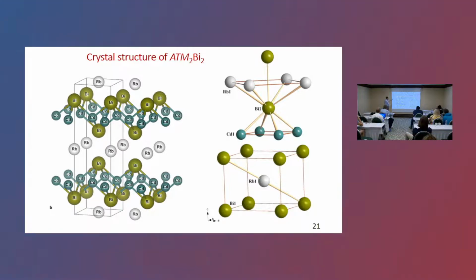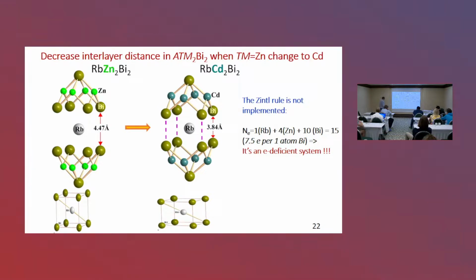This is the very important layer responsible for superconductivity. And we can see the alkali metal between these layers. These are the polyhedra of iron, of rubidium and bismuth. And it is very interesting that the distance between the layers may change very strongly if we change small zinc to big cadmium. The reason for this very big change in the distances is, I may say, mechanical,